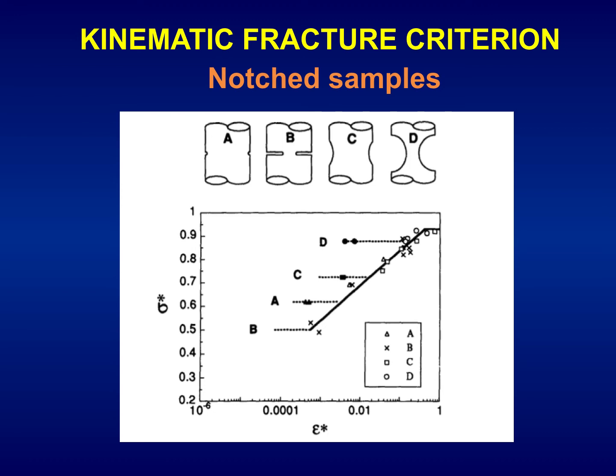Here we have the results from notched samples. They will be explained in another presentation in this conference, but again in dimensionless terms: dimensionless stress computed using the average value of the TTS region, and dimensionless strain, the notch tip strain rate averaged in space over the tearing topography surface and over the test duration to failure. Here we have a universal curve independent of the geometry, for 4 different notched geometries with different levels of stress triaxiality, a common curve, and 4 different asymptotic values depending on the triaxiality levels, B, H, C, D, resembling BACH, the name of Johann Sebastian Bach, the most genius, the best musical composer ever.